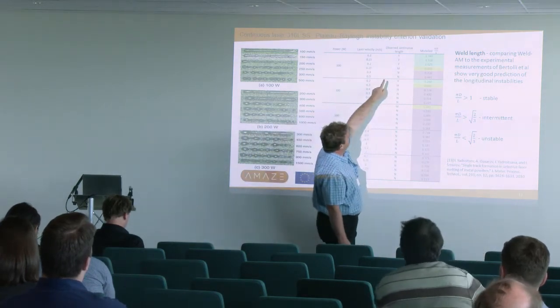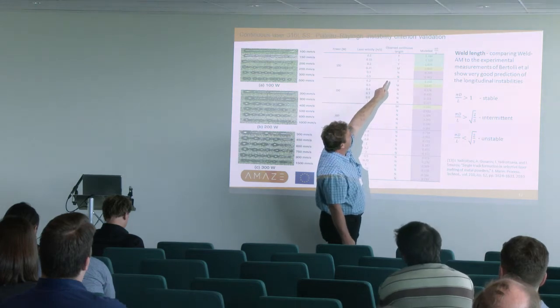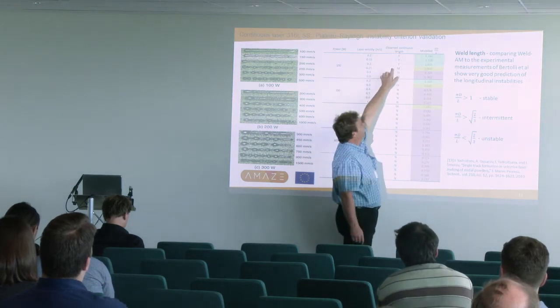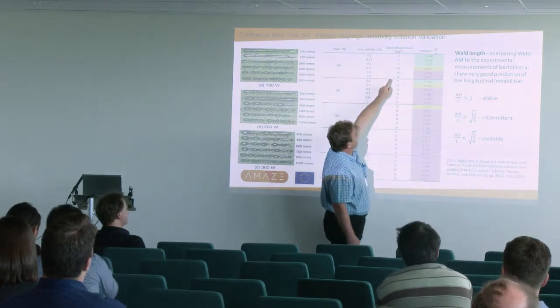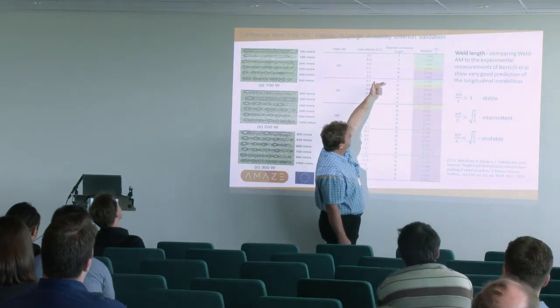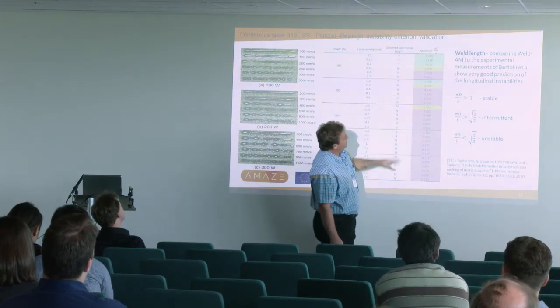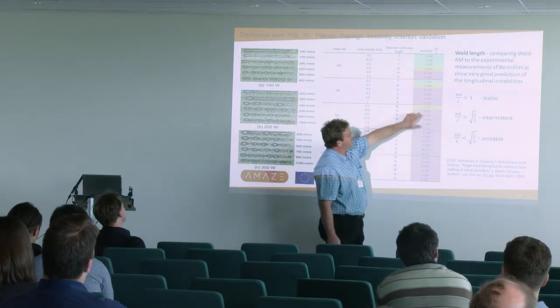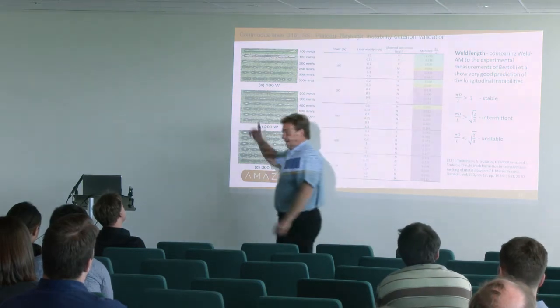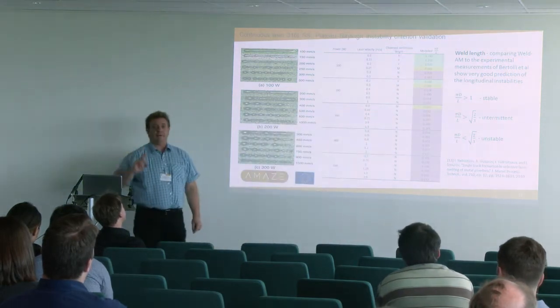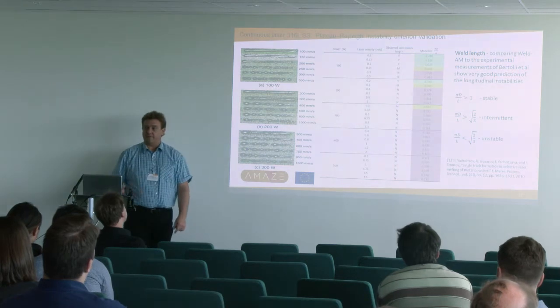You can see this continuous length here, it only really happens for these three dots here with the lower velocity and the lower power. So you see continuous length, and all the rest are noes. The red ones here are basically noes, these are possibly, and the green ones are yeses. So that simple model with that simple criterion is matching what we're seeing in the experiment.